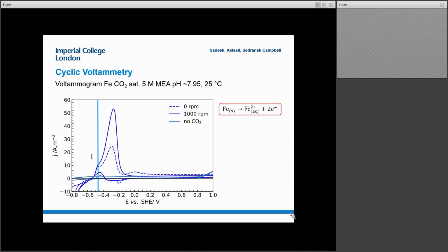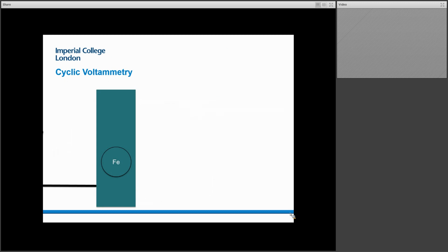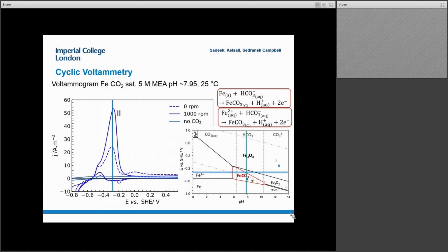And what you can see in the first instance is we have iron oxidation. So we have the formation of iron ions. But where this gets interesting, so this is our first step, which we have previously illustrated. Okay, where this gets interesting is what's now happening. So as we move our potential in our CV, what we begin to see is the additional reactions taking place. And what becomes interesting is trying to determine what those are and using those thermodynamic predictions as a methodology for basically providing an undercurrent for what might be happening. And so in this first instance, we believe that this is due to a reaction forming iron carbonate.